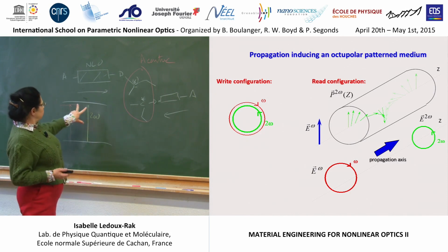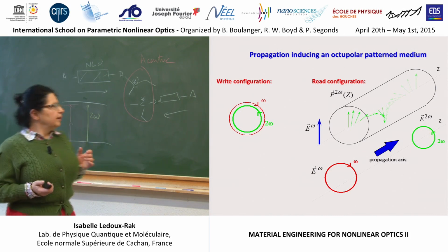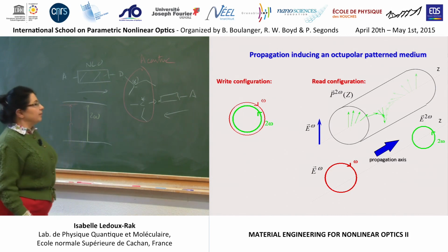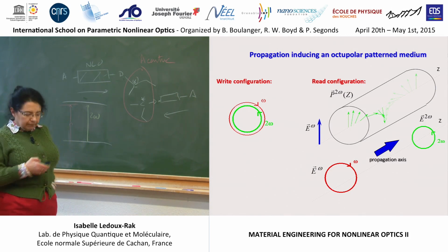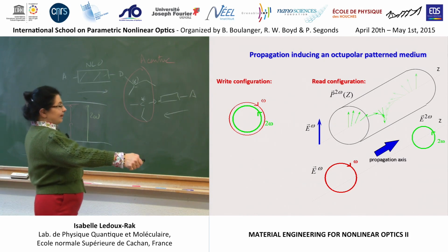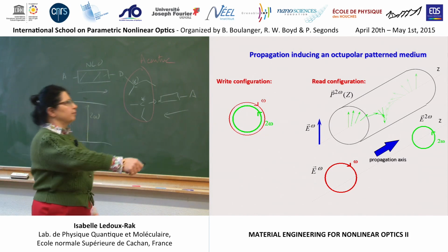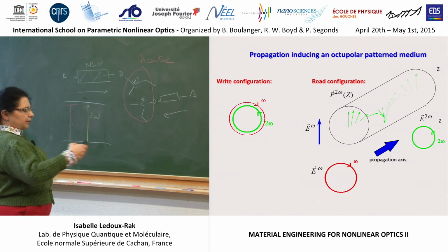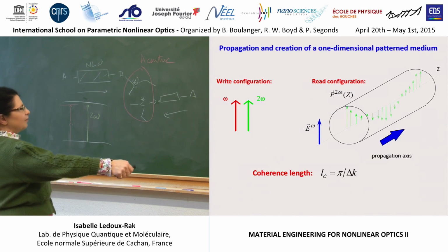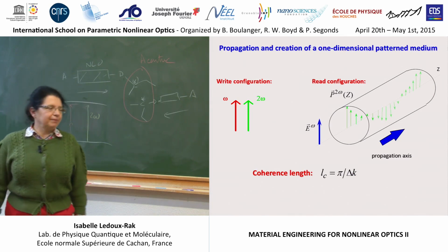So if this energy is too far from the excited state responsible for isomerization, then there is no poling. And it means that the medium is strongly absorbing, and that such kind of periodicity, because the coherence length will be a few microns typically, or maybe a fraction, is in practice difficult to observe over a length larger than 1 or 2 microns. This is the main problem.